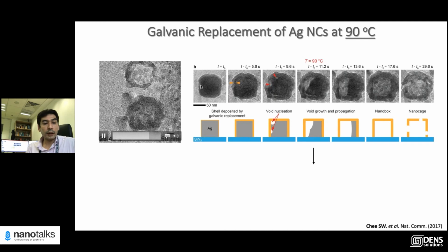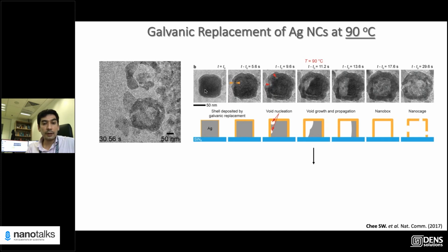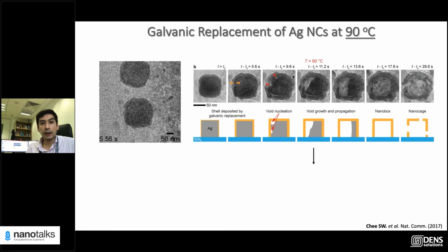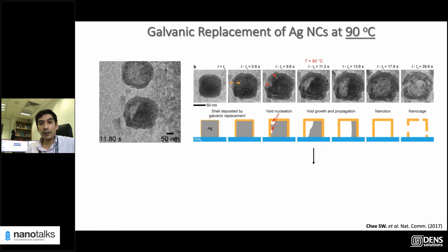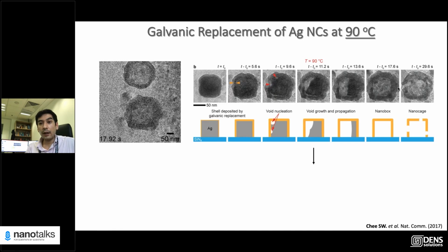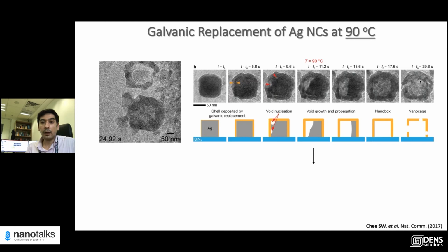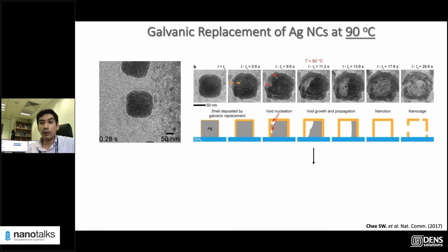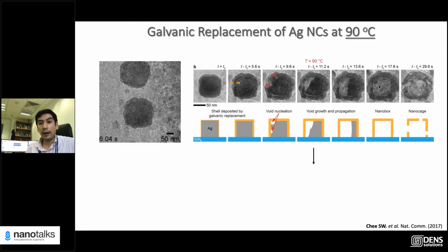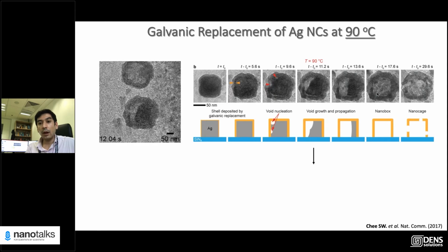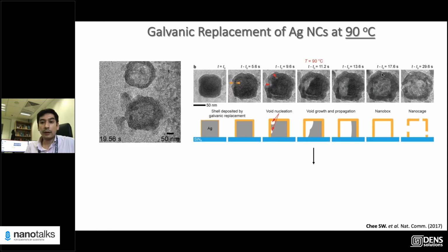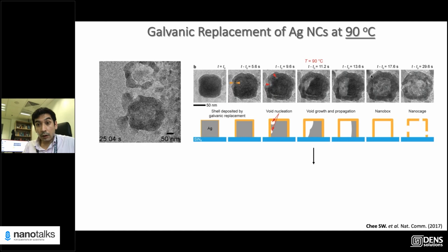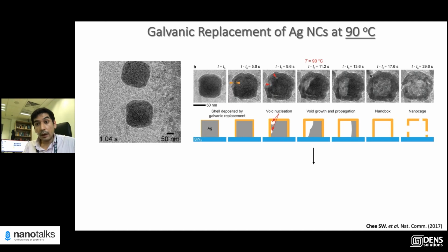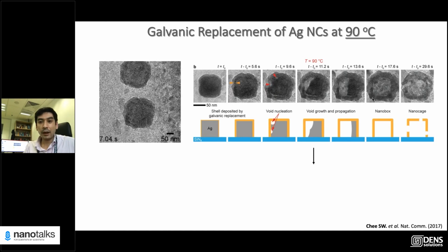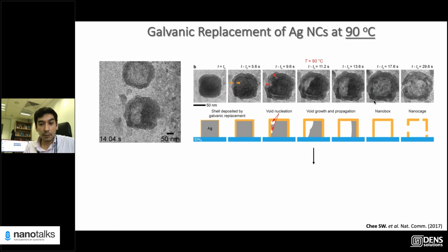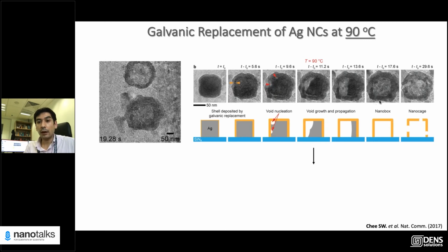So what you see here is the shell deposition. This is the thickness, and you see the pits forming, and pits predominantly form at the edges, and then they kind of eat away, right? They kind of eat into the silver, and silver dissolves, and you have these hollow nanoparticles. Note we do not observe any holes, but it's really hard to say from these images. But I'm going to come back to this point in a bit.